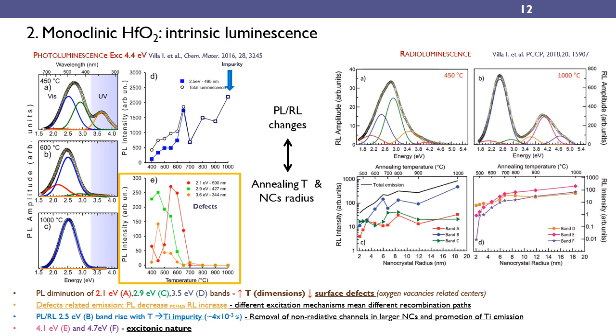If we consider only the decreasing bands, the photoluminescence picture reveals that these bands may be related to surface defects, supposedly oxygen vacancy related defects. Indeed, while the temperature is increasing, the size of the nanocrystal is increasing, that is, the number of surface defects responsible for the emission is reduced.